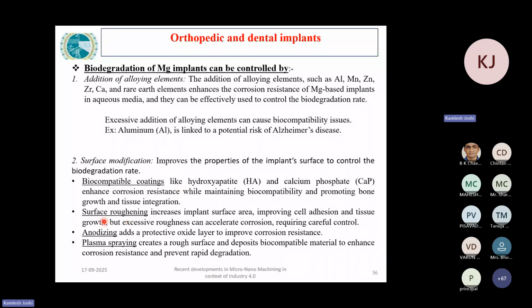Another way is to control the surface roughness. Controlling the surface roughness improves the cell adhesion and tissue growth, which helps in osseointegration, but excessive roughness has an adverse effect and can accelerate the corrosion. So we have to carefully play with the factor which is surface roughness, because on one hand it improves the tissue growth on the implant, on the other hand it accelerates the corrosion.